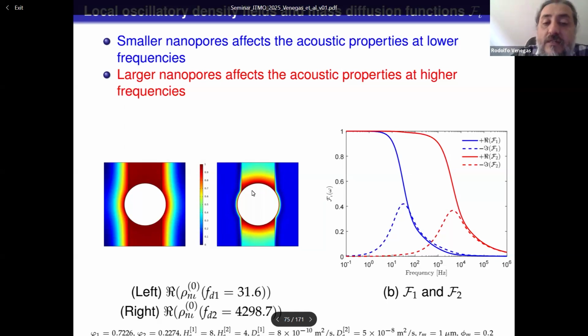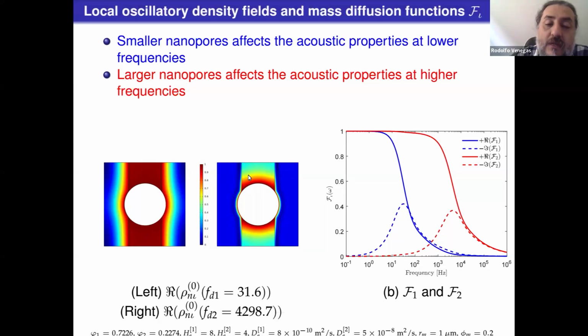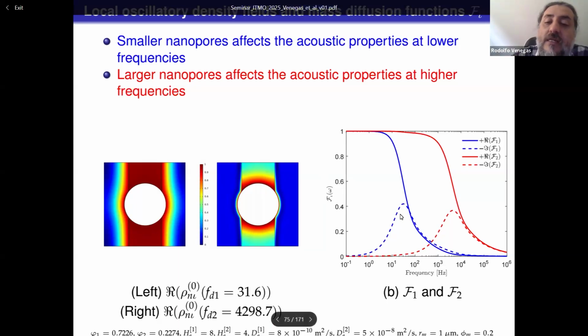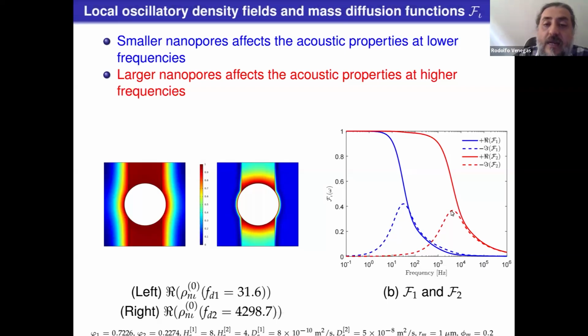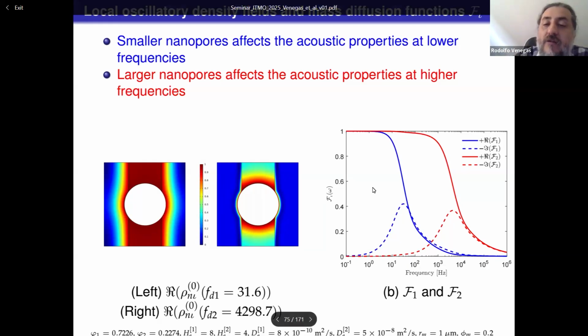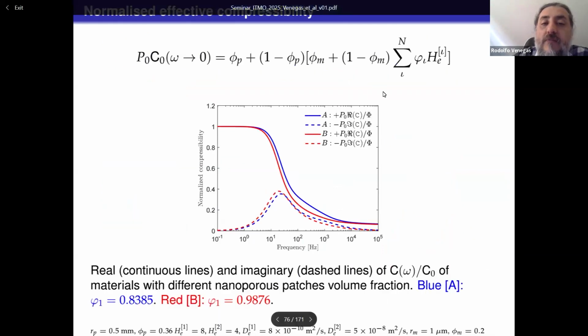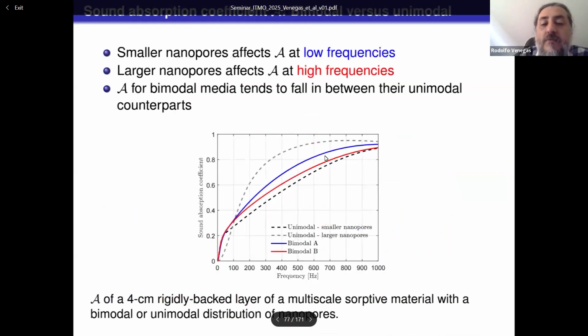But what we can do by changing the nanopore size, and therefore the linearized sorption equilibrium constant and diffusion coefficients, is that in one of these mass diffusion functions we'll have a peak related to dissipation of sound energy at low frequencies, and the other one at much higher frequencies. So we can use that to tailor the response and affect low frequencies with one type of nanopores and high frequencies with a larger type of nanopores. This is an example of normalized compressibility that, despite the fact that it doesn't look very different, it does have some difference when we look at the sound absorption coefficient.